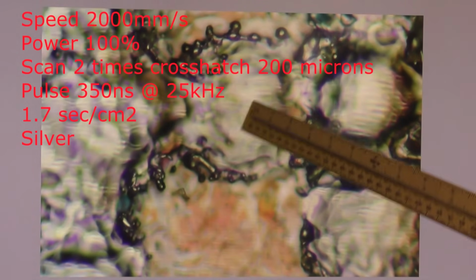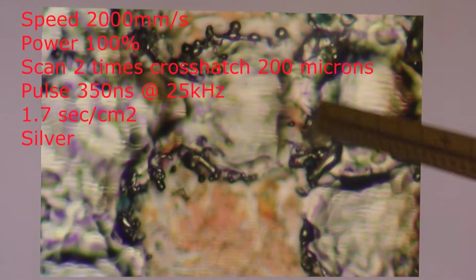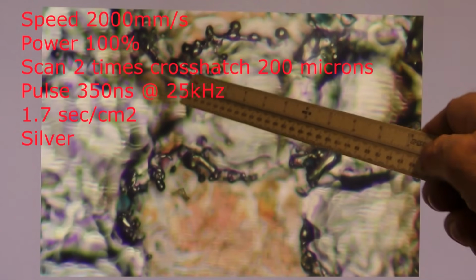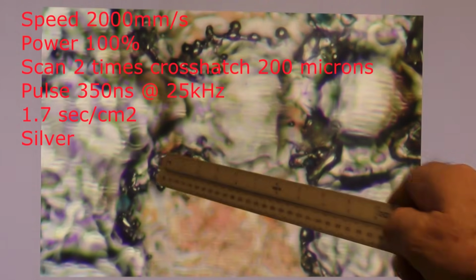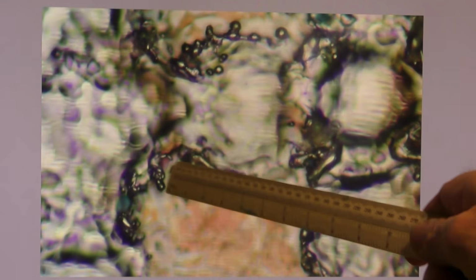So what you're able to see here is individual pulses. And look at the metal that's splashed up around each one of these pulses. As soon as the liquid stainless steel hardens, and it must have been liquid to produce these blobs, we get an oxide film that is created on the surface. As I mentioned to you probably in an earlier session, from all the reading that I've done, this oxide film forms within a few nanoseconds of the metal being exposed to oxygen. So there will always be a film of some sort on the surface of stainless steel because of the interaction of chromium and oxygen. And that effectively is freezing the colour into the surface.